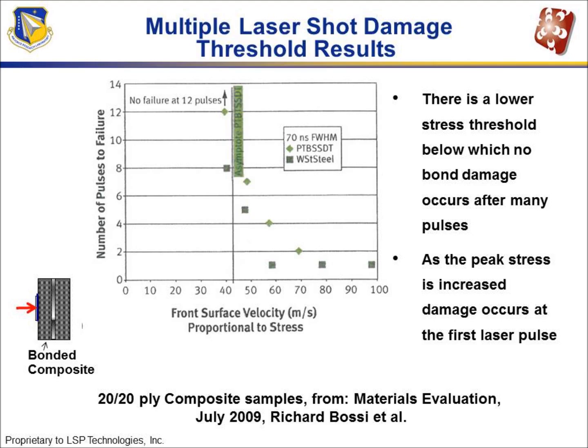In this particular case, we graphed the number of pulses to failure as a function of front surface velocity. You can see at the higher velocities, that means a higher stress and higher fluence level. That's where you're doing the damage, and it only takes one shot to break the bond. But as you go to lower velocities, as you get into the region where we're doing bond detection, you can see that it asymptotes out, that you get to a point below which you don't see any failures even after multiple shots. So this is an indication that laser bond inspection can be used without interfering with the strength of the structure.